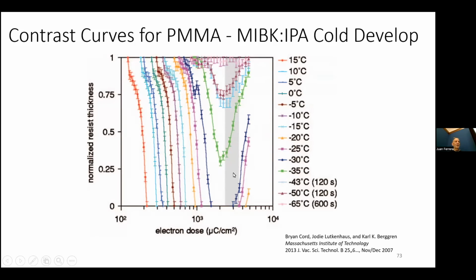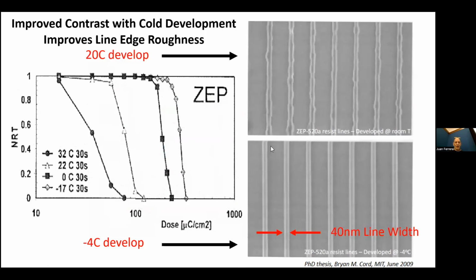And it turns out as you have to give it higher and higher dose, you get to a point where the chains in the polymer, instead of getting broken up and getting washed away, they cross-link to each other and you start getting negative resist. But that's probably not what I should bring up in this talk. The same thing will work for O-xylene and ZEP for developer.